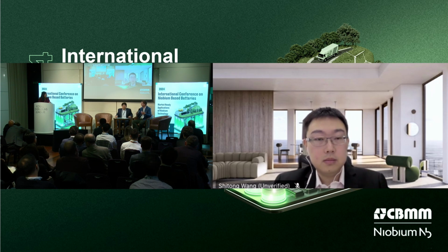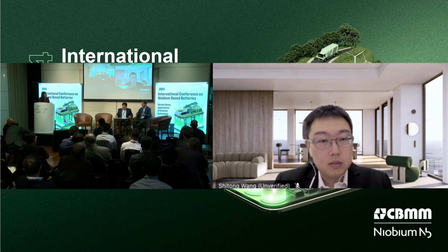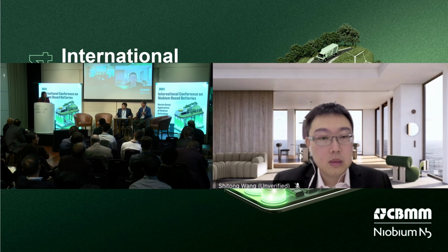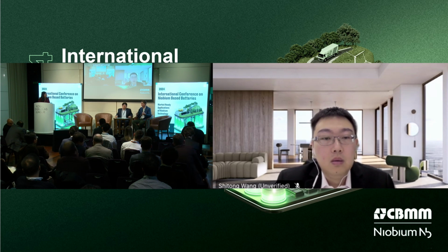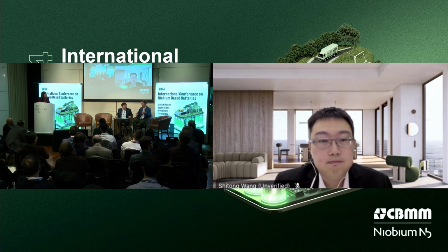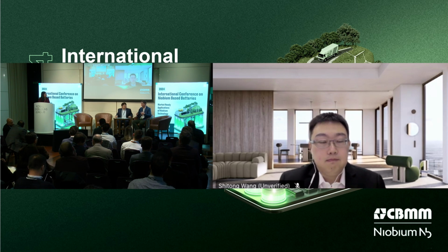But we've shown that's not the case after you use them, and they never go back to that state. So it really doesn't make sense to think about them conceptually like that. These are active electrode materials. Their properties are changing dramatically, and so you have to think about their conductivity over their use state of charge range. So that's the first point.